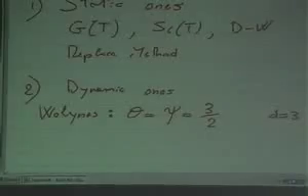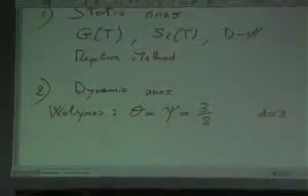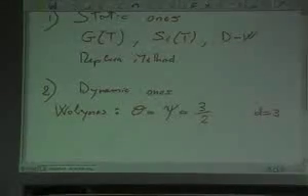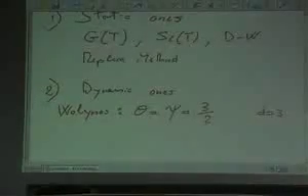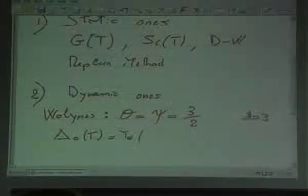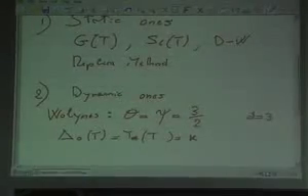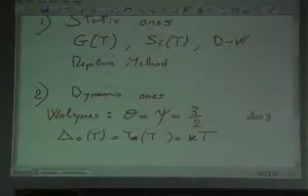There is the original Kirkpatrick-Thirumalai-Wolynes paper, and then there are other papers in which they discuss why theta should be equal to psi, which should be equal to 3/2. The other important thing is, if you look at the expression that I wrote down there, there is an upsilon, which is in the surface tension, and there is a delta 0, which is coming in the expression of the relaxation time. What Wolynes says is that upsilon is actually a function of temperature, which is equal to k, a constant which is more or less equal for all supercooled liquids, times the temperature.